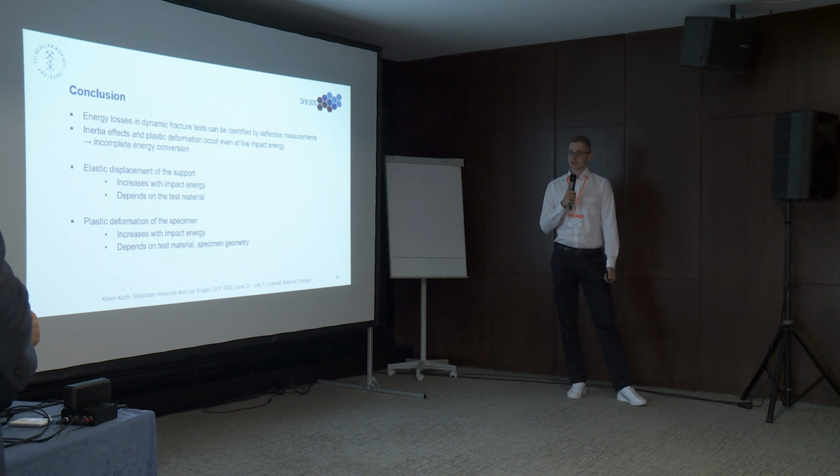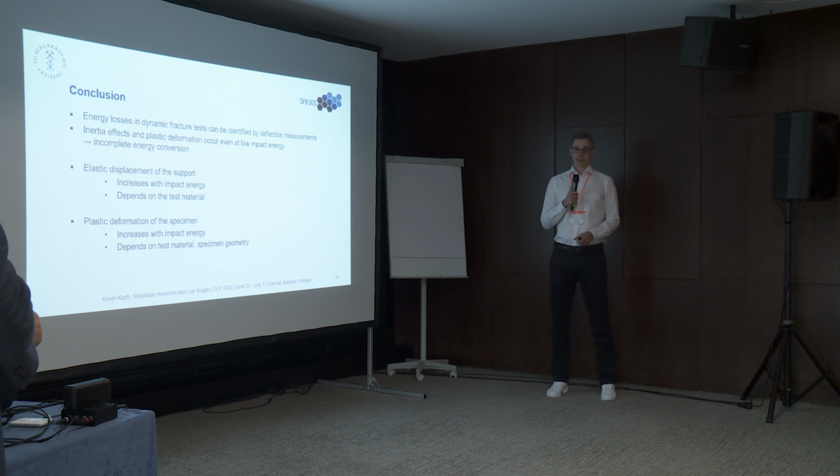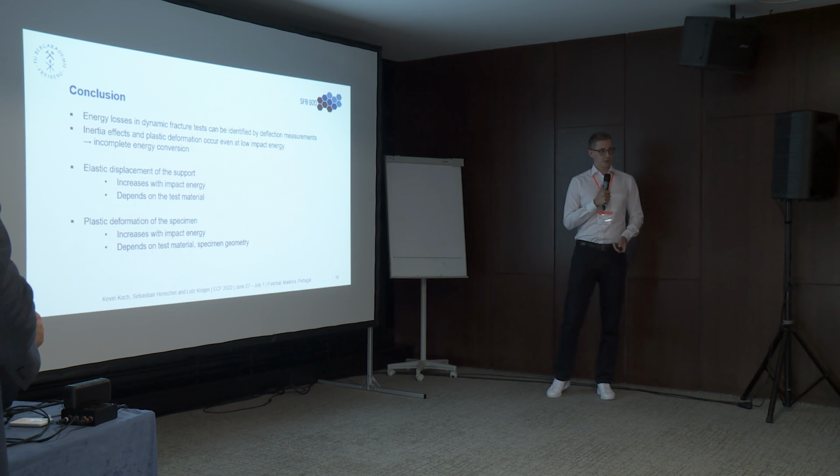Our second factor was the plastic deformation of the specimen, which increased with impact energy and also depended on our test material and the specimen geometry. And I have to add that these effects may be specific for our test setup that we used.